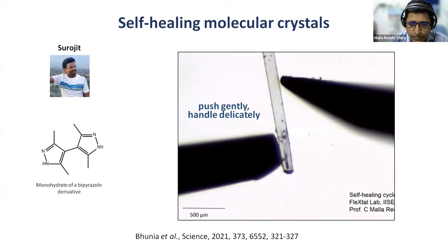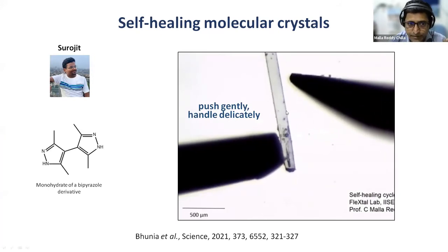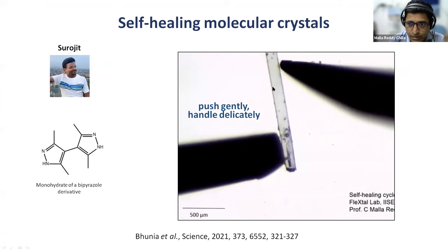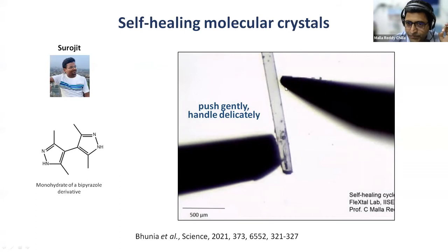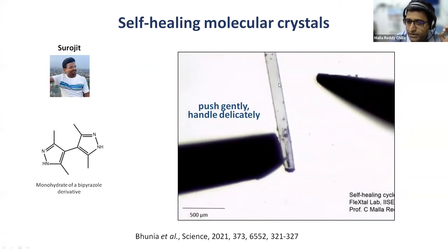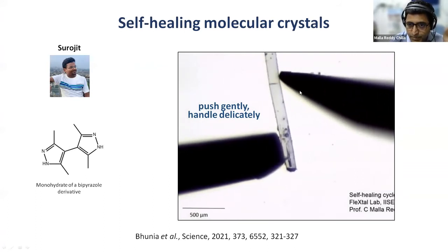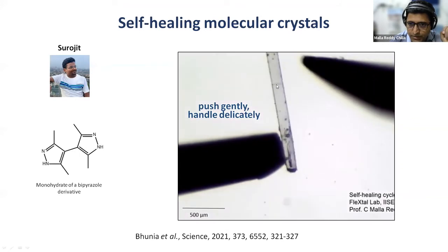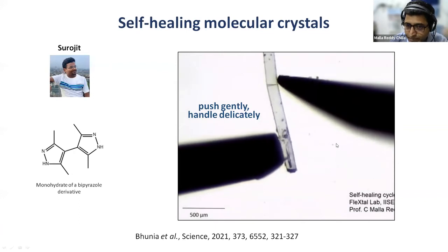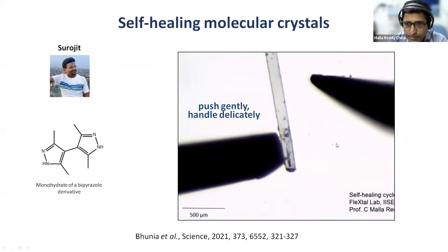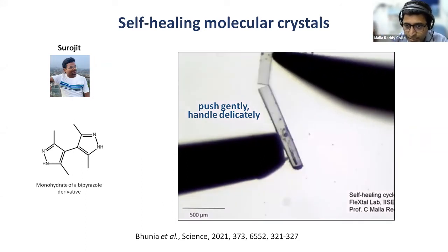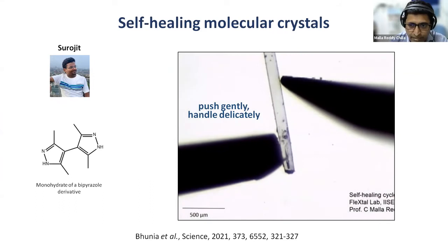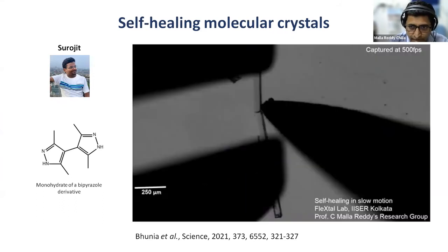But when you apply the mechanical stress gently, my student Surojit found that these crystals break, and then they heal the crack very efficiently. But when you push very hard, then this crack does not heal properly, as you can see here. Here you can see that the crack remains when you push them very hard, but when you push them very gently, most of the time you see that the crack heals completely, and you can't find any sign of the crack that existed there.